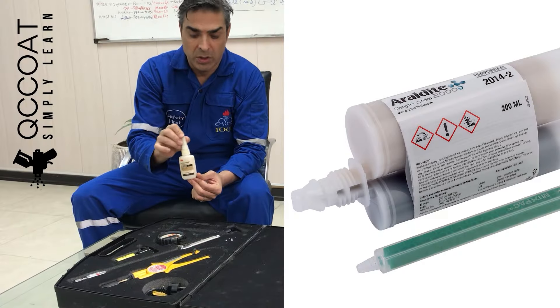According to the ISO 16276-1 standard, the following are important. The minimum thickness of the substrate must be 10 mm, a lower thickness requires a special fixture. In this standard, it is mentioned that the device type, device manufacturer and surface temperature during testing should be mentioned in the report.